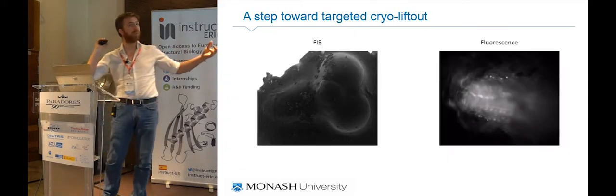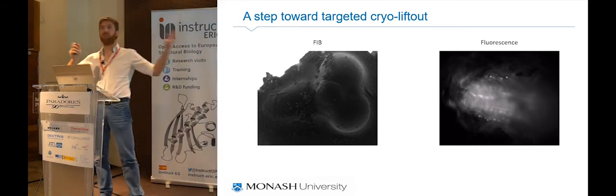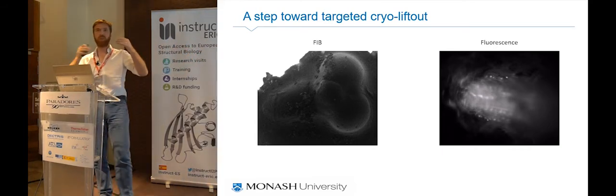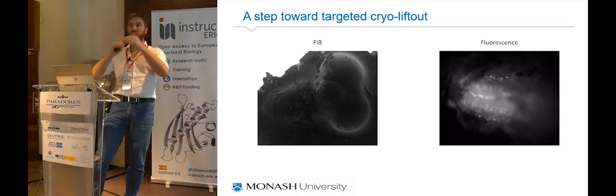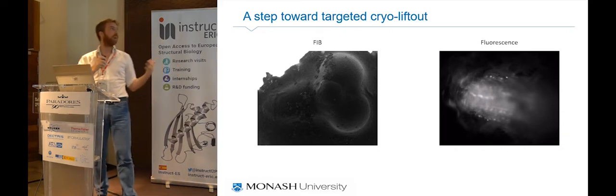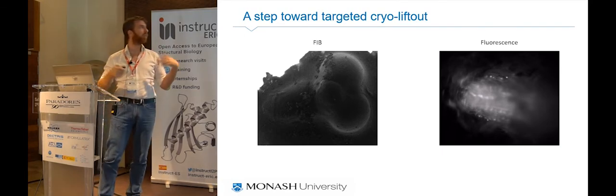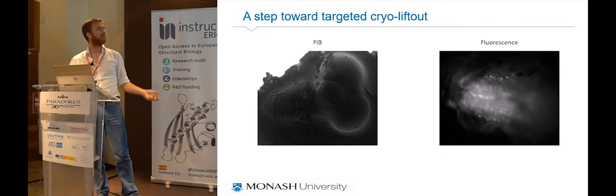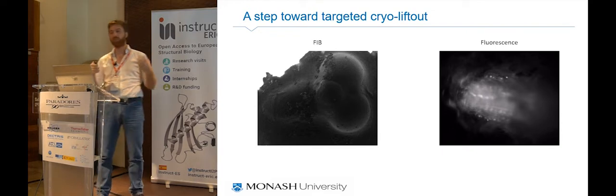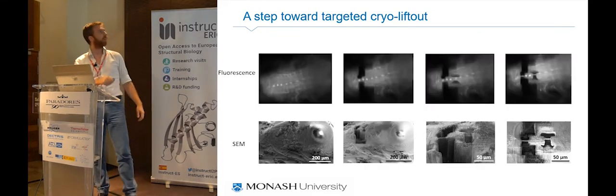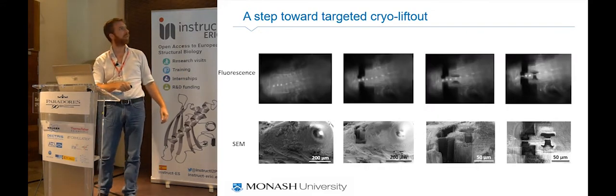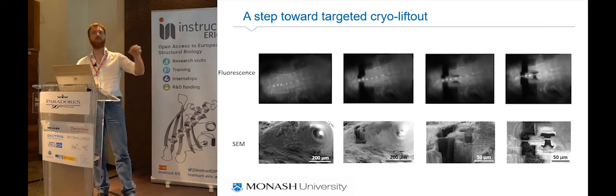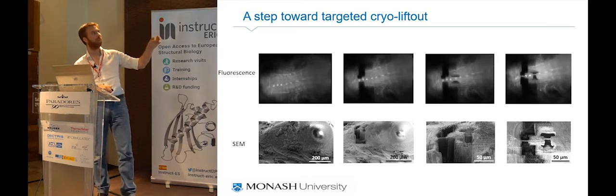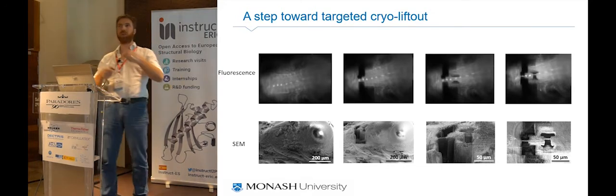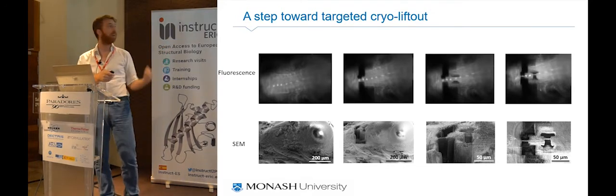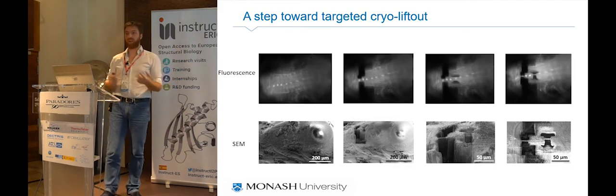Another thing, for example, if you want to do cryo-liftout, which is what Julia was showing, it's really important that you're actually lifting out what you really want to lift out, because the whole process takes forever. So here is a Drosophila brain, which was also frozen, and we have some interneurons which are expressing GFP. We start milling, top and bottom, and we make lamellas which are ready for lift out. And we're sure that we're making them where we want them, on the spot. And we're sure that they're on the spot because you can see the spot in the lamella. And this is really handy.